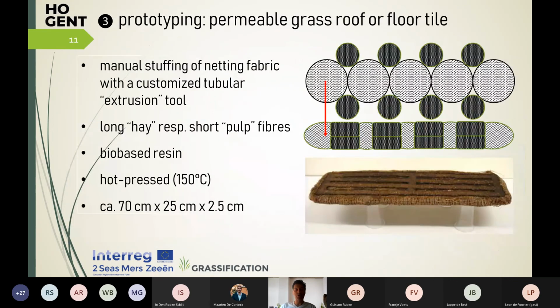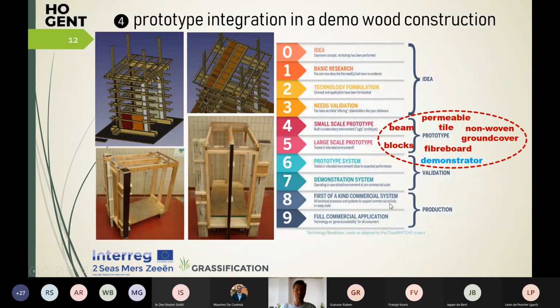And finally, the last prototype is a roof or a floor tile material. You see on the right-hand side how it was made in cross-section. We stuffed a netting fabric with grass fibers mixed with a bio-based binder, which was also pressed to this tile shown at the bottom. This tile is about 70 centimeters by 25 centimeters wide and about 2.5 centimeters thick.